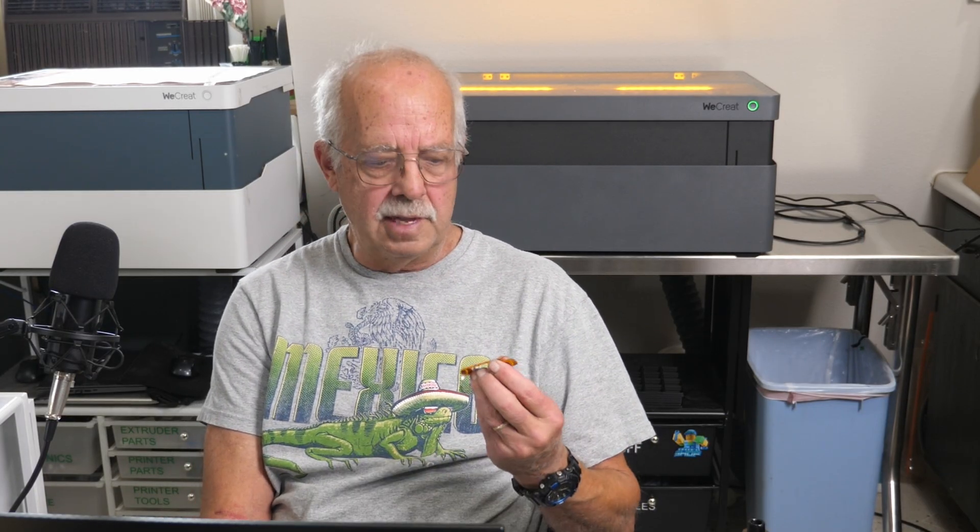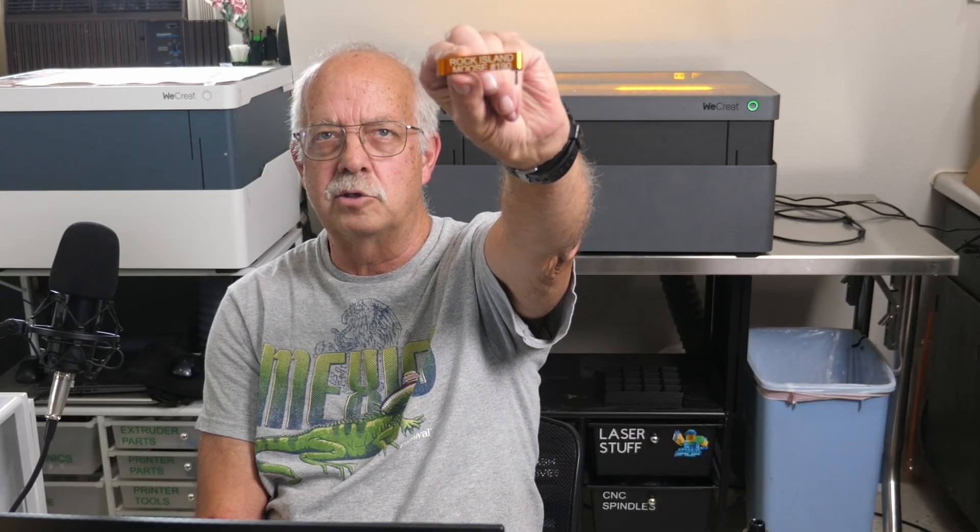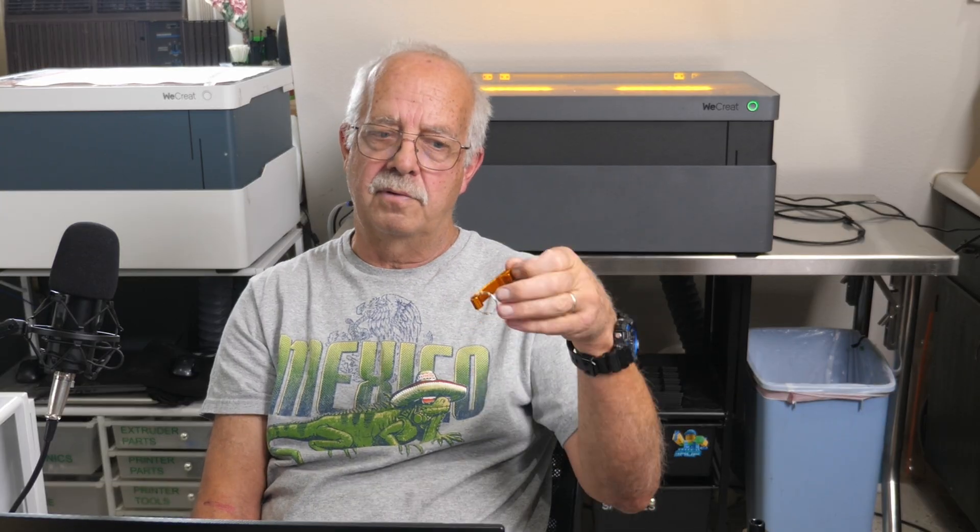So it's processing and it will go on and do its thing, and I'll come back in three hours and take this next batch off. So we got a little bit of noise going on now because I've got the laser running behind me here. But that's how you make these bottle openers like this. And like I say, you get lots of different colors when you buy a bag of those, and the ones you cannot use without coating first are the silver ones because there's no anodizing on them and they will not etch. But all of the other colors - the gold ones and the blue ones and the purple ones and the red ones, the black ones - all etch the same with the same setting: 78 power, 10 millimeters per second.